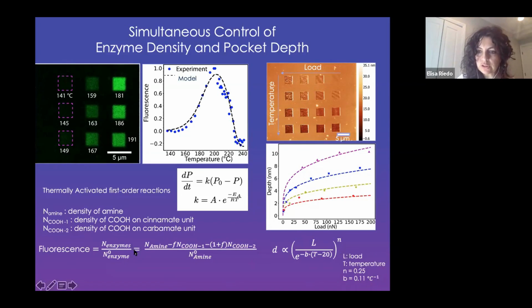And these are the two main equations that we are using. So we are using a modified Hertz model, modified because we assume that the Young modulus of the polymer becomes lower and lower with increasing temperature. So we can quite well control the pocket depth by increasing the temperature, because the softer the polymer is, the more for the same pressure we can make a bigger indent. This is what this equation is telling us. And with the load, the higher the pressure, the bigger the indent.